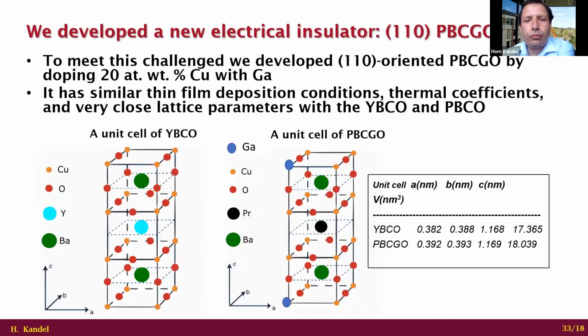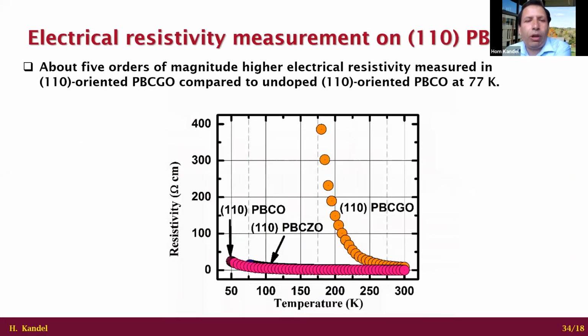Next slide, please. So we have developed (110) PBCGO, a novel electrical insulator, which is almost similar to YBCO, as demonstrated by this lattice parameter here and also the perovskite structure here. It also has similar thin film growth conditions. Next slide, please. Likewise, the electrical resistivity of this material is very high. For example, compared to PBCO, the traditional insulator, which is a very poor insulator, it has almost 5 orders of magnitude higher electrical resistivity at 77 Kelvin.